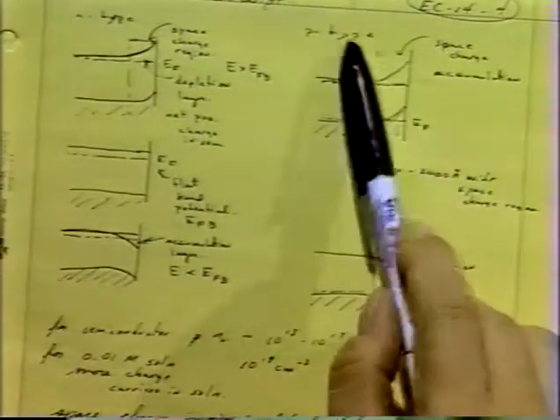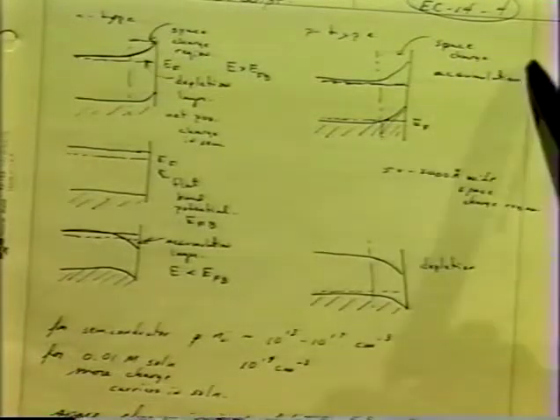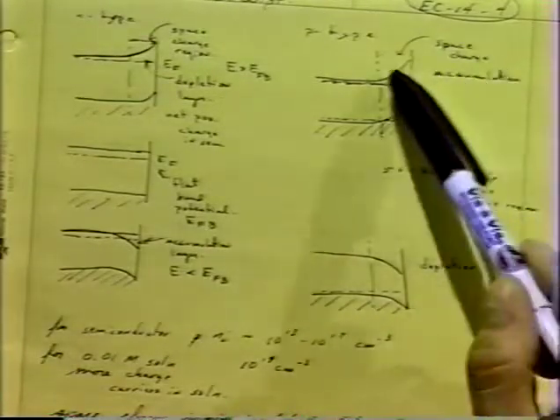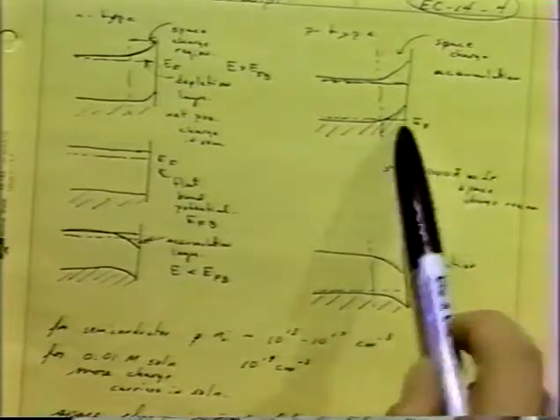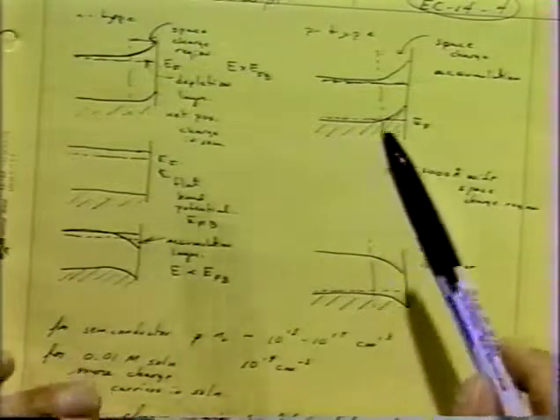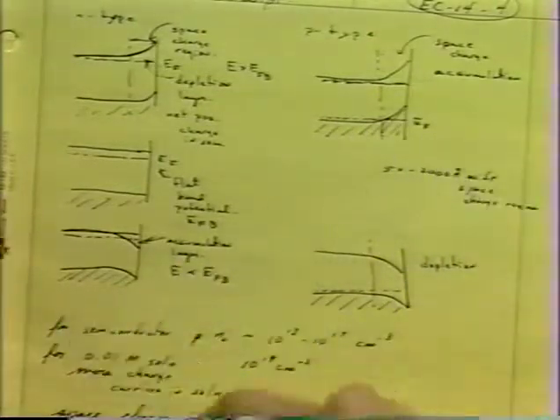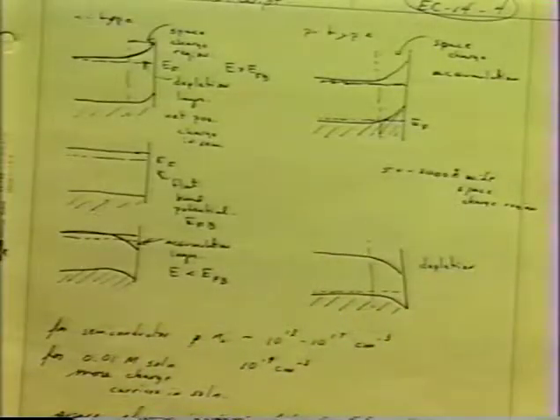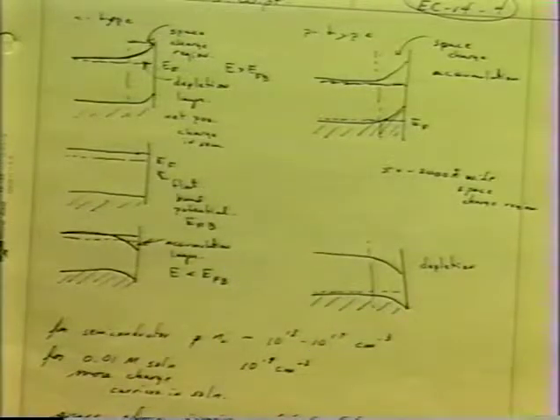A p-type system is analogous. In this case, we'll get an accumulation when the bands bend up because now we have an excess of holes in the system. Under these conditions, the bands bend up because electrons have come out of the semiconductor into the solution, because we have a positive charge on the semiconductor. But in a p-type, that means we've got an excess of majority carriers, which are holes to begin with. So now those fill in the valence band, and we have an accumulation layer of holes. So again, in a p-type system, when the bands bend up, we're going to get a metal-type conduction.